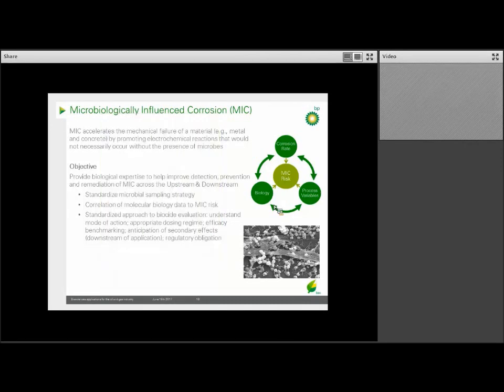Another area of concern is microbial-influenced corrosion, or MIC. MIC is the influence of microorganisms on the kinetics of the corrosion process of metal, caused by the microorganisms adhering to surfaces — what we call biofilm. Microorganisms in pipelines can attach to surfaces, embed themselves in slime — what we call the extracellular polymeric substance, or EPS — and form layers of biofilm. These can be very thin, think of monolayers, but can reach the thickness of centimeters. These biofilms are characterized by strong heterogeneity, and how they start, their adherence to the metal surface, and how they grow is critical in our understanding and remediation.